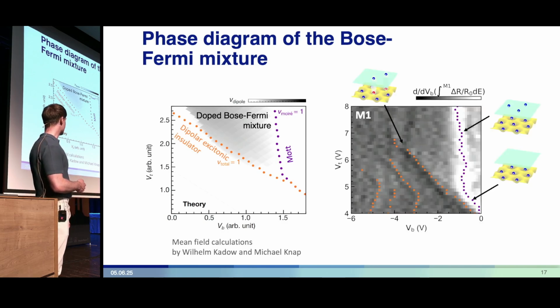This theoretical phase diagram actually matches very nicely with the experimental phase diagram, where we've extracted, using the 2s exciton, the incompressible phase shown in these orange dots. That's the dipolar insulator up here. And then the Mott insulator, which we are deriving from the kink in the Moiré exciton.